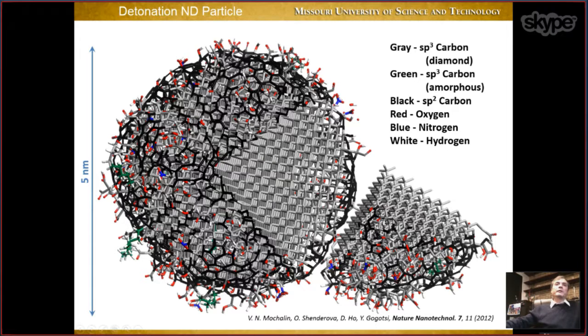The core of the particles is made of diamond, so this is diamond structure here. And the surface is terminated with many functional groups. And this black stuff here is sp2 carbon, because the dangling bonds on diamond surface have to be either terminated by heteroatoms forming functional groups, or they will combine with each other and form sp2 carbon on the surface. So this is why any nanodiamond has some amount of sp2 carbon on the surface.